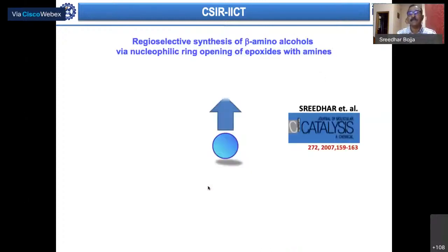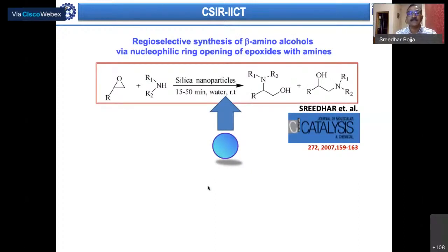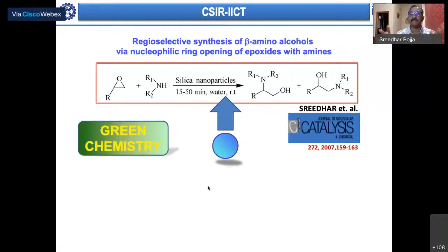I will give you some examples here. Initially, we started with silica nanoparticles, and this was the reaction we worked on. What is important is that this reaction was done earlier also, but using harsh conditions. In our case, we tried to work at room temperature with water as the solvent, adopting the principles of green chemistry. That is why this gave us a lot of interest.